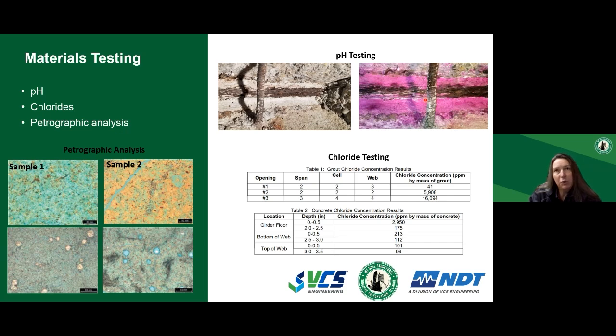If there is a suspicion that there is environmental exposure to chlorides that is leading to chloride contamination of the grout, it is a good idea to test the chloride concentration of the concrete surrounding the duct, in addition to testing the grout. So in this example, we collected 3 grout samples from different tendons. Sample 1 was collected at a high point, samples 2 and 3 were collected at low points of the drape.